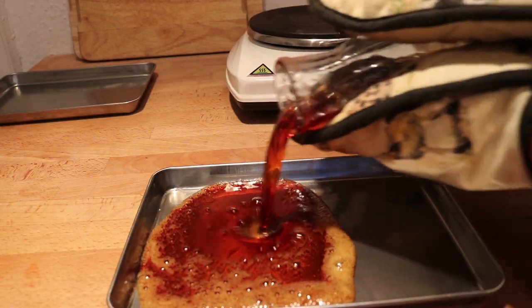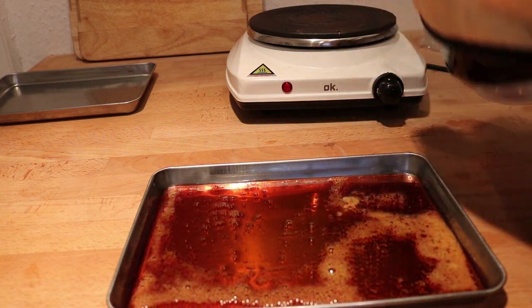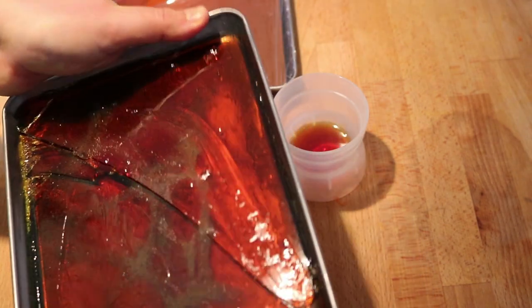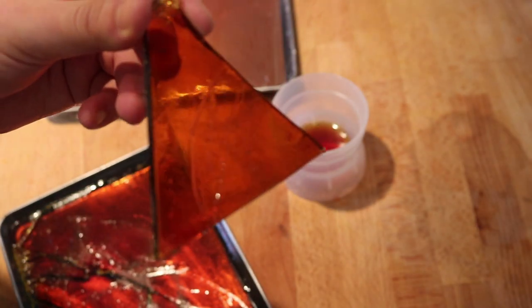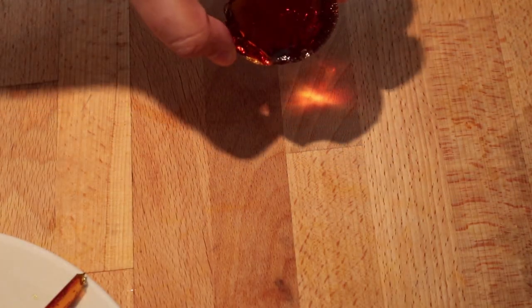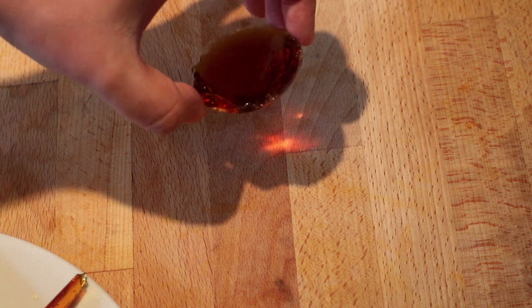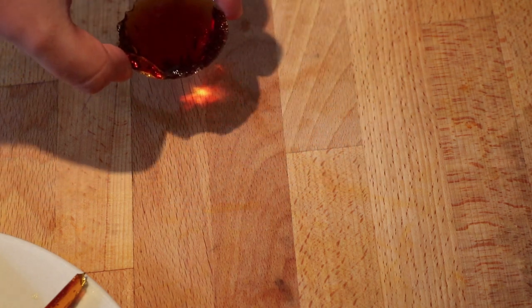Be careful when pouring this into the molds because sugar burns are a really nasty thing. We're just going to want to let this cool — somewhere around two hours later should be good. Because I was feeling lazy, I actually returned to this the next day. And here you can see it turned out awesome. I got really flat, clean sugar glass with very few air bubbles. The color was a bit off, but it acts like glass — it completely snaps and breaks. The second batch also turned out pretty good, and I'm happy with it. Now what about this lens? It kind of cracked a little on the surface as I pulled it out, and because of the spherical shape of the mold, it suffered from some really bad spherical astigmatism. Maybe I can get a parabolic mold sometime in the future. But in any case, it still kind of works. It's been super gray and rainy here, so I can't really use sunlight to focus down and burn a piece of paper or something, but I probably could if I had sunlight.